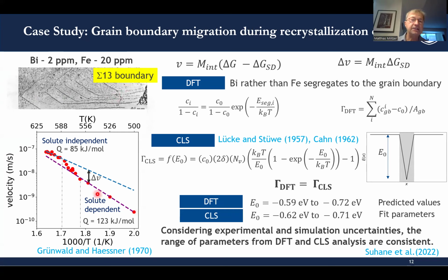Now, what Grünwald and Haessner found, they measured the velocity of this grain boundary at different temperatures and then made an Arrhenius plot and did see deviations from a classical Arrhenius behavior. And so there's two Arrhenius branches, one at higher temperature, one at lower temperature. The argumentation was, well, at higher temperature, the grain boundary moves without solute interaction. At lower temperature, there's an interaction with the solutes. And then we have a transition range. We can extrapolate the high velocity branch to lower temperature. And the velocity difference that we see here can be interpreted as the effect of the solutes in terms of solute drag.